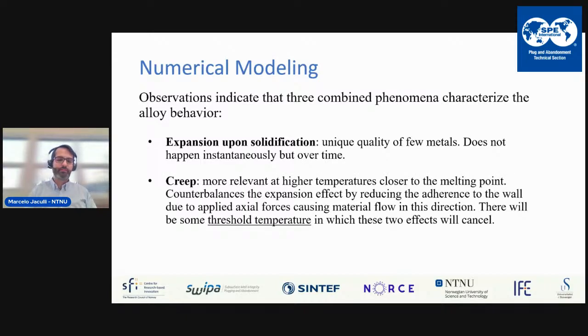In parallel with this effect, you have creep effects, which become more relevant at higher temperatures, closer to the melting point, counterbalancing the expansion effect. We noticed that if you operate at temperatures very close to the melting point, creep is so significant that you cannot keep the plug in place, and it won't resist any pressure. So there is a threshold temperature, the maximum operating temperature for that particular alloy.